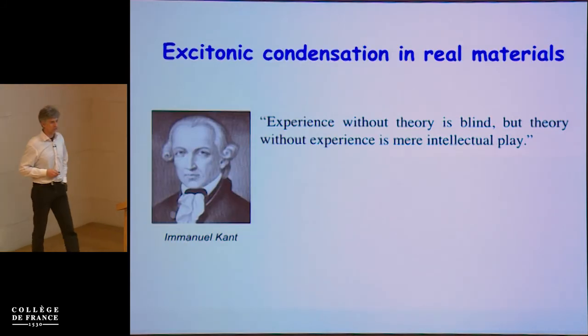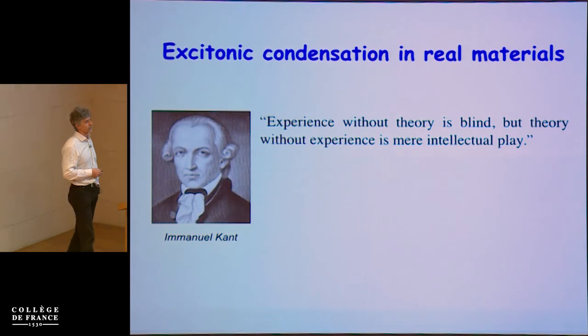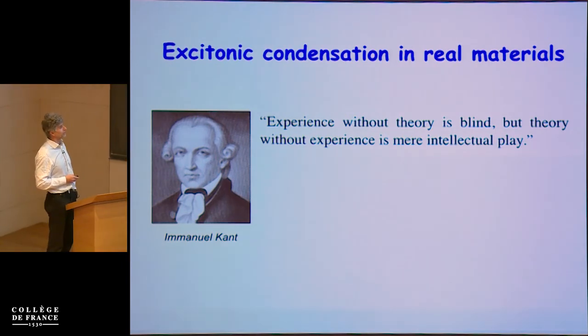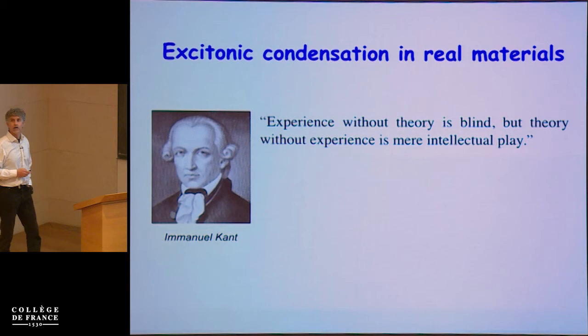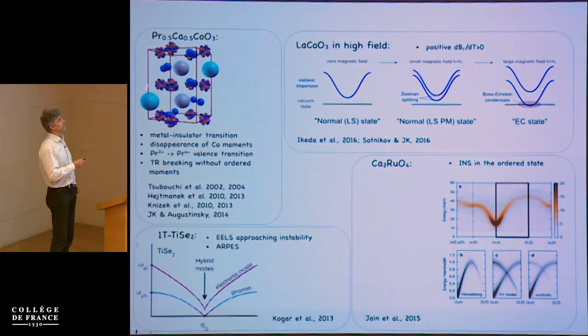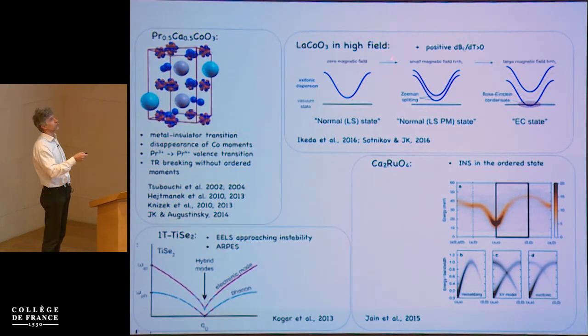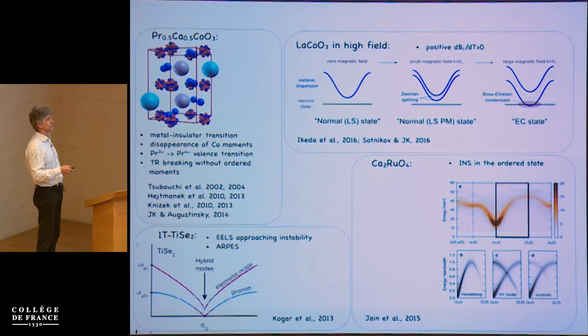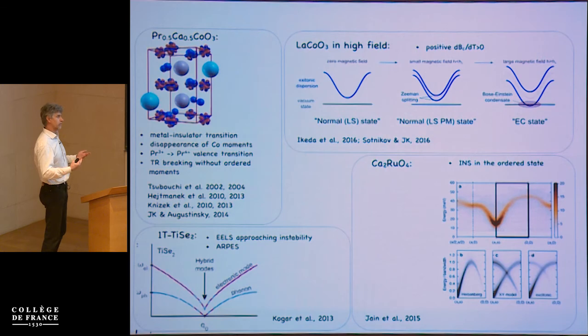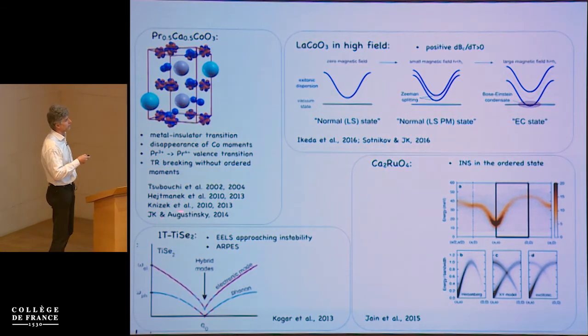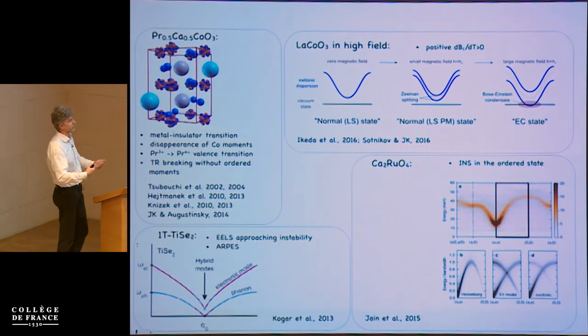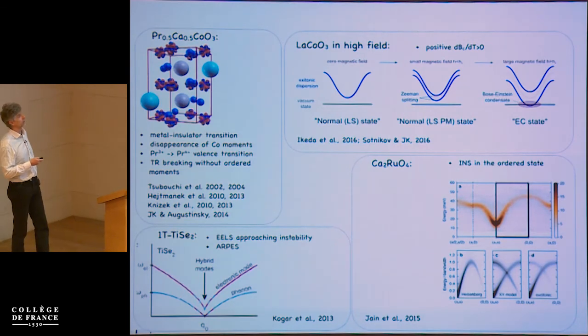Let me finish with the models here, and go down to the ground to look at real materials. There are several examples that may be promising: praseodymium calcium cobaltate, perhaps lanthanum cobaltate in external field, calcium ruthenate, and also materials which are now almost proven to be excitonic condensates, which are not magnetic, where the excitonic condensation actually takes place in the spin singlet channel.